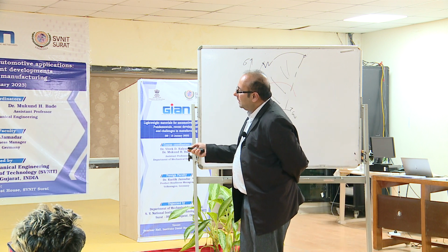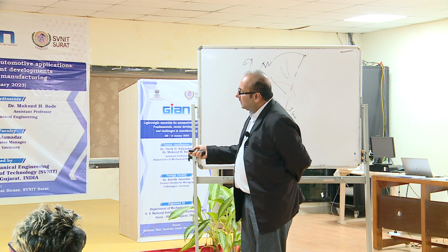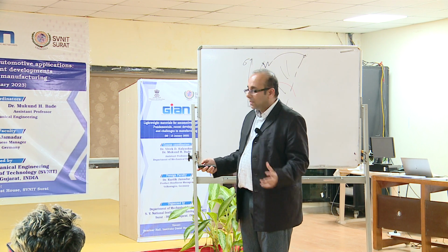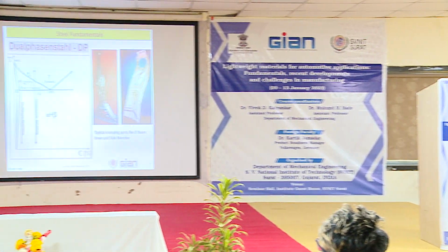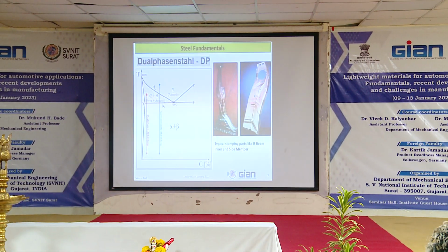So this is about the dual phase steel. You basically here in this area, you heat it faster, quench it faster, but then you go slowly so that you have both ferrite as well as martensite. You normally get around 500 to 600 MPa and quite good formability.